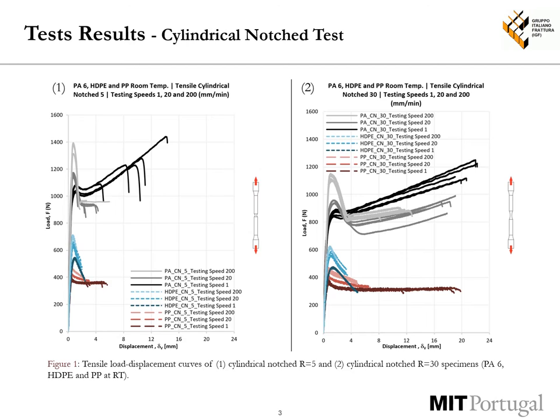Test results on cylindrical notch specimens reveal that higher cross-head speeds increased both the propensity of the materials to form a neck and higher yield load. The yield load also increases with increasing specimen notch, increasing the stress triaxiality.